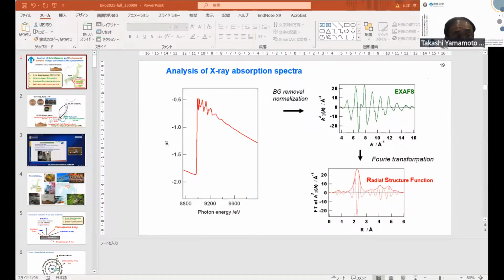Then these are the typical analysis procedures. This is the X-ray absorption spectrum of the copper foil, and this is the fine structure we can see like this. Firstly, the background is estimated and removed. Then, after the background is removed, we normalize to the edge jump like this.